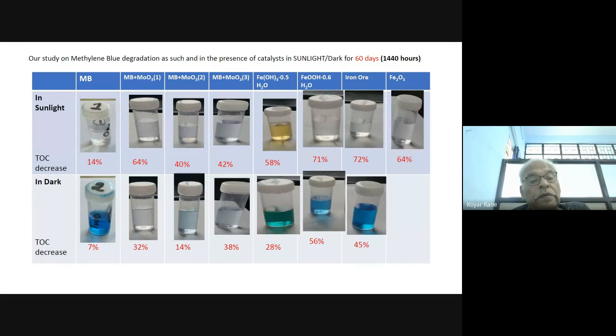When I put the catalyst in sunlight, you can see that there is a tremendous increase in the TOC removal. It means molybdenum oxide is removing the methylene blue. Almost 70% methylene blue is degraded, but there is still around 35% organic matter left. We don't know what it is.